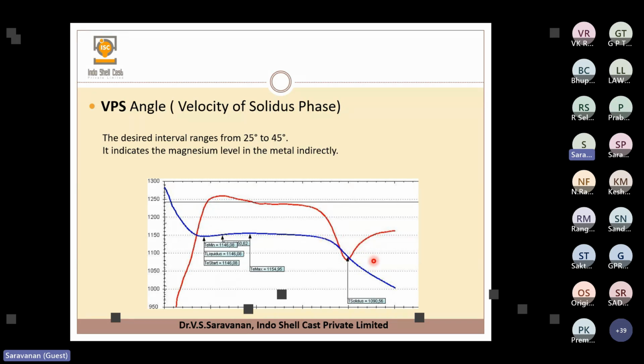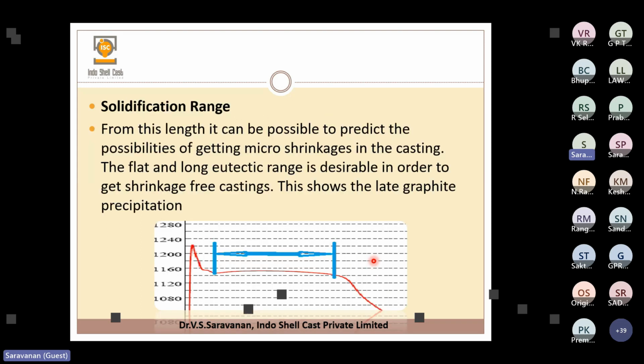Sometimes we add more magnesium, and that is also not good. If we add more magnesium, from the nodularity point of view it is good, but again it will create a lot of issues like shrinkage porosities. More magnesium actually promotes shrinkage. Then magnesium related oxides, sulfides, all these defects will come. So we should always limit the magnesium to the minimum extent. That is very important. For that, some software has the provision of measuring these angles, and then we limit the magnesium content also. So this is the solidification range I discussed earlier. This shows the late graphite precipitation.